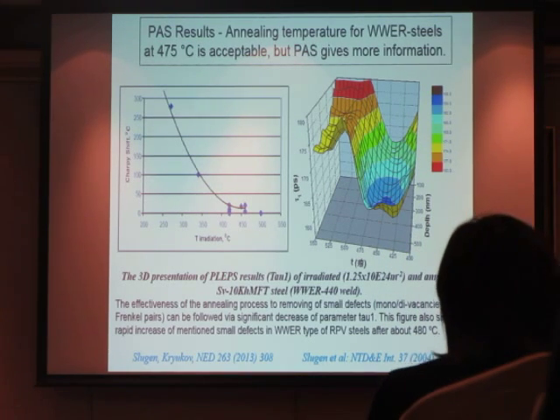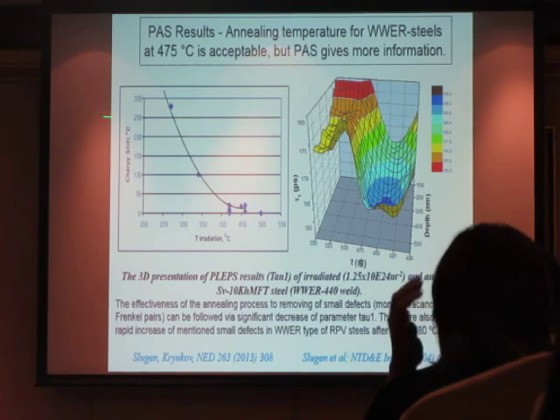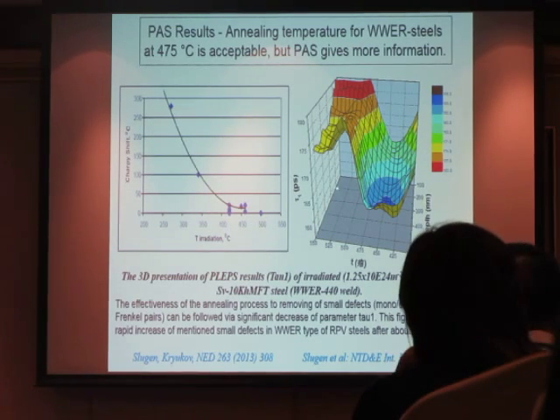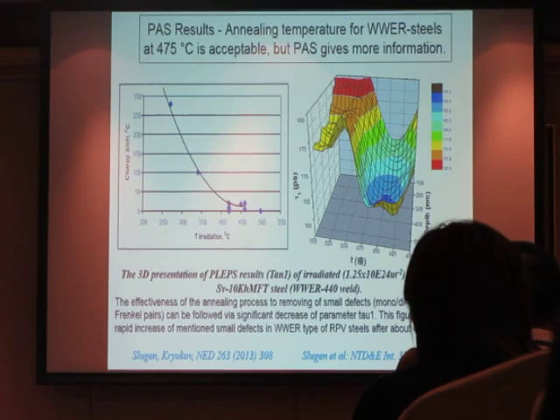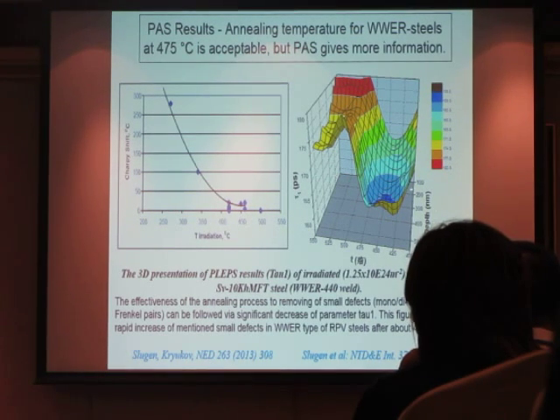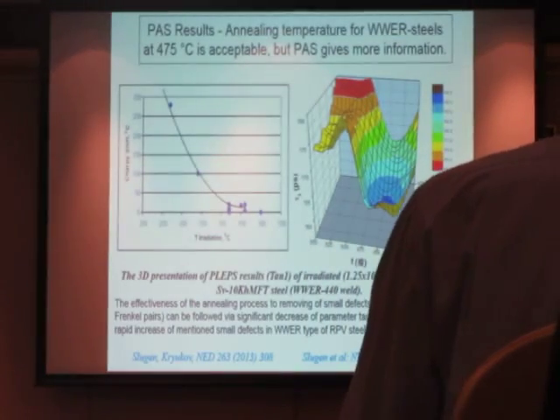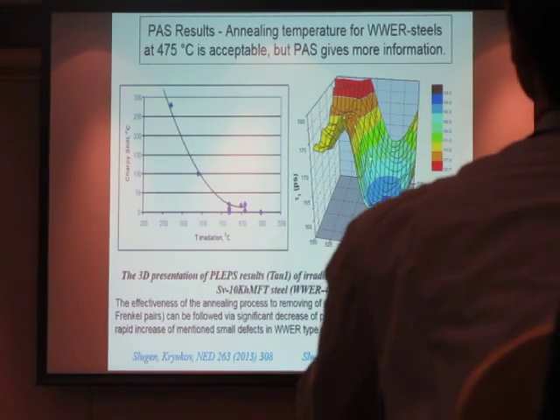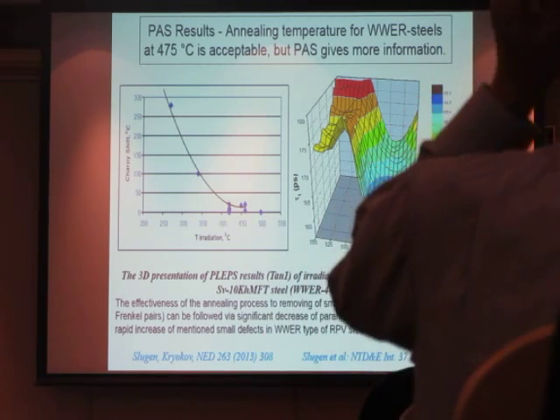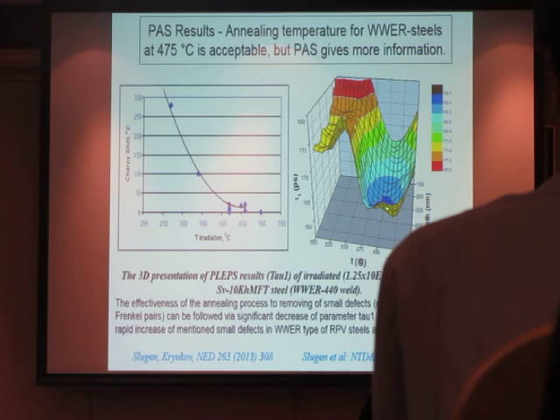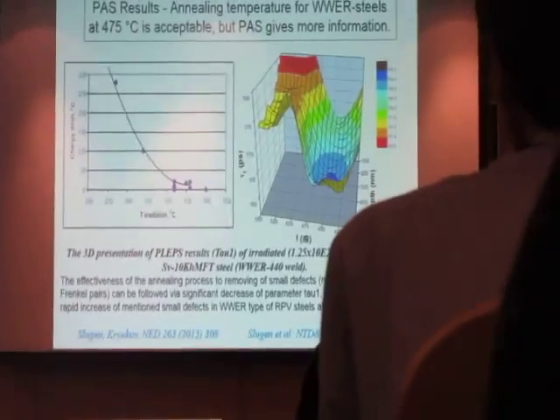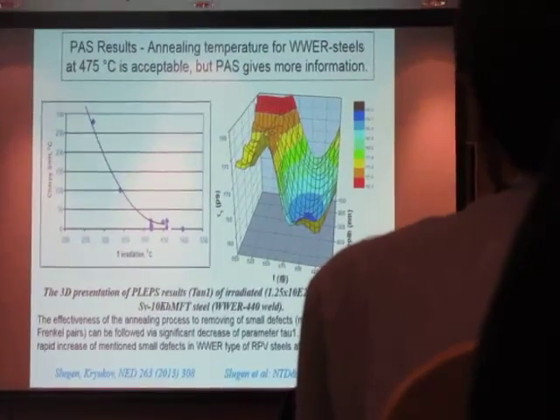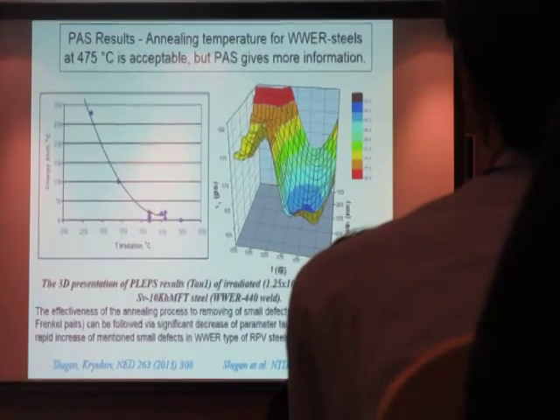This is important for the industry. Industry believes only Charpy V tests. So, in the past we had irradiated reactor pressure vessel steel, and in this plot all these points were measured. It's not simulation. It was measured by me in Munich somewhere in 2002 by the labs. Each point was measured, and you see the plateau of the best condition, annealing of most defects by 450 degrees Celsius. But if we go to the Charpy tests, it's the proof as well.